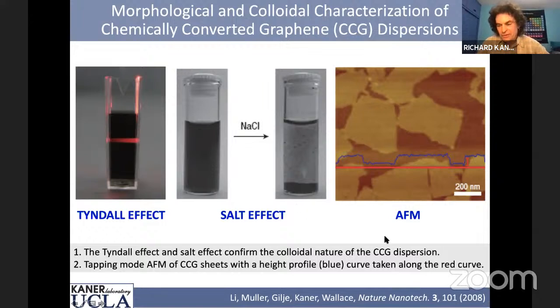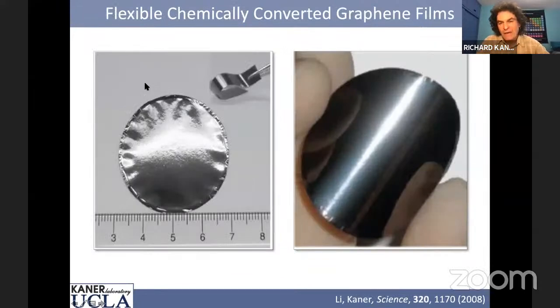We published this in Nature Nanotechnology, and this paper has been cited over 9,000 times. So it's a very popular paper on how to convert graphite to graphene oxide and then back to a form of graphene. And once you have that, we've got large quantities of graphene. We can just take a beaker full and run it through filter paper, and we can trap carbon, and we can make chemically converted graphene films. And so we just peel it off the filter paper. And so this is graphene piled up, literally tens of thousands of layers.